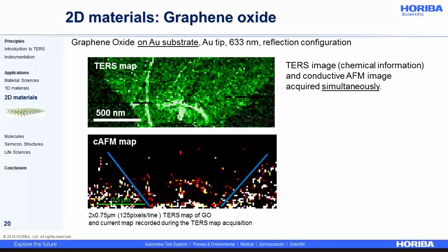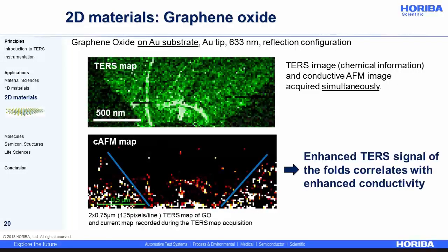In the conductive image, one can observe that the region where the pixels are more intense, corresponding to enhanced conductivity, perfectly matches the folds and the wrinkles of the graphene oxide in bright green on the upper image, suggesting a direct correlation between the conductivity and the TERS signal of the folds of the graphene oxide.